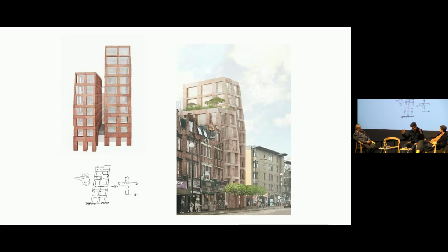So we could double or quadruple the amount of limestone, but then I think Pierre said, well, you can try basalt, born from fire. Let's test that. It was a quarter of the amount of the material you need. So a quarter of the amount of extraction, a quarter of the journeys by truck and lifting, and a much stronger material than the Clerkenwell material.